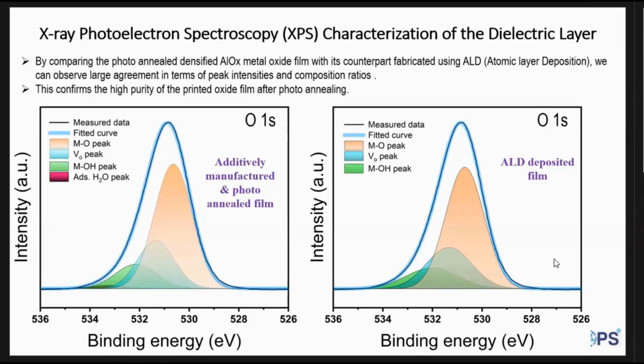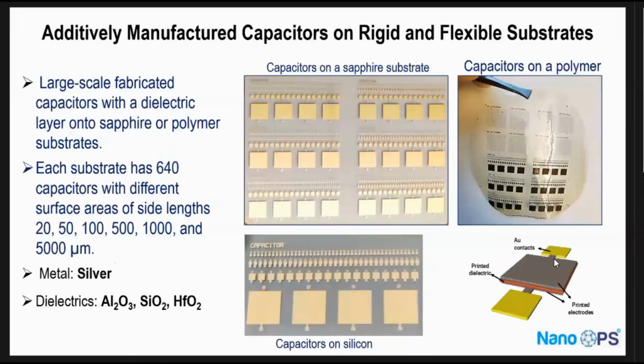Then we moved on to printing the capacitors. These are the capacitors that we made. Typically, in each sample we have about 640, and we made a variety of sizes, from 20 by 20 micron capacitors to 5,000 by 5,000 micron capacitors. We use mostly silver metal here, and for the dielectric, alumina, silicon dioxide, as well as hafnium dioxide, all done in the same way. We also did it on polymer. You can see in the corner there, the substrate in this case is parylene.